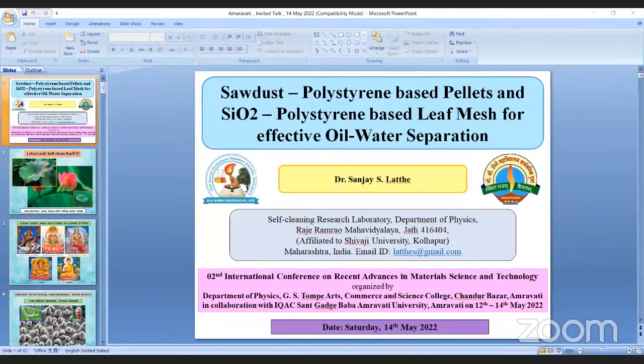Next one. So you can see what we did: we collected the sawdust from the sawmill, and this is the raw sawdust you can see on the petri dish. We filtered it using a stainless steel mesh with a pore size of 50 micrometers. So the sawdust we collected, after drying, is of size 50 micrometers. Now we mixed this sawdust in polystyrene to make the sawdust-polystyrene composite and kept it for overnight drying. So we get the sawdust-polystyrene pellets. These pellets can be used for oil-water separation. You can see the setup of oil-water separation: the pellets are put in this setup and the oil-water mixture is passed through them, so you can easily separate the oil from the water.